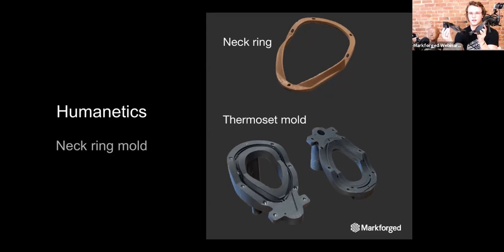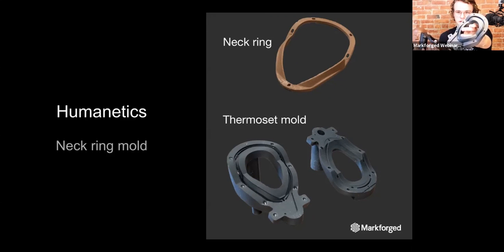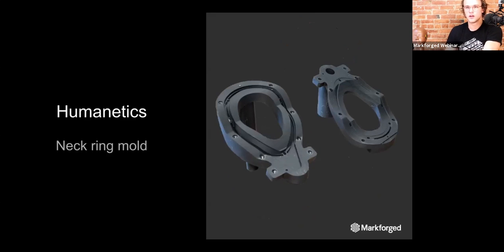And so it's a two-piece mold. And if you look inside, you can see that neck ring shape. And it's pretty complex. This mold is tilted at this angle. And we were able to print it into a two-piece mold that fits together like this. And so Onyx, which is our thermoplastic, is able to give it a really, really nice surface finish all over this part. And they reinforced it with HSHT, which is our high strength, high temperature fiberglass. And that helps the mold retain its shape during the heating and clamping process of making the actual part.